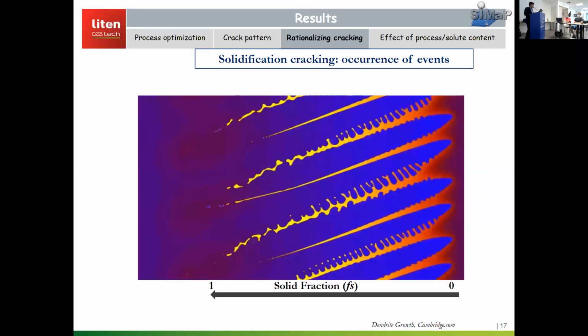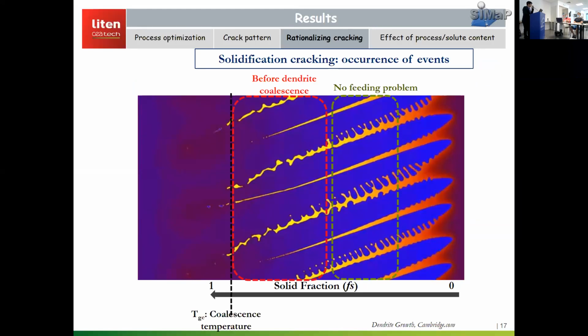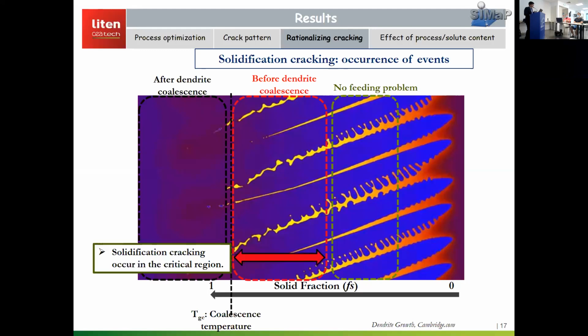So to summarize these occurrences of events as a function of solid fraction, for low solid fraction, we have easy feeding of liquid, so no feeding problem. The second region can be identified as before the dendrites start to coalesce. After the coalescence point, we can have good transmission of the mechanical strains to the neighboring dendrites. So before the coalescence, it is most critical for cracking, and after coalescence, you have a more resistant mushy zone. So the solidification cracking occurs in a critical region.